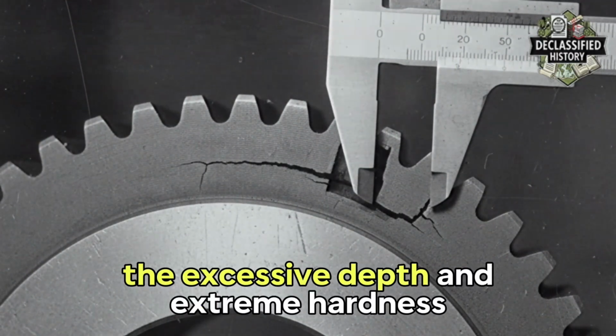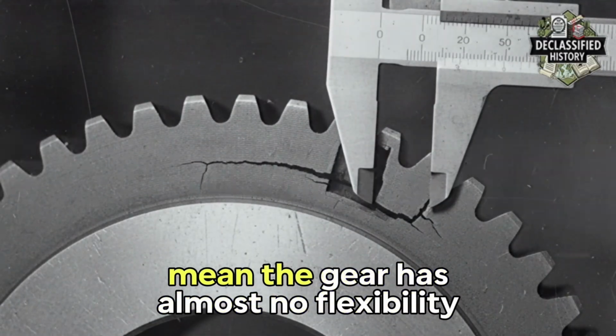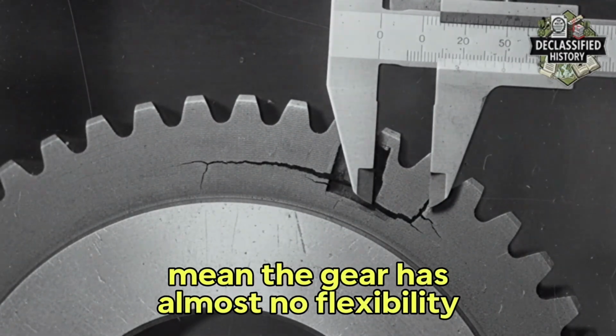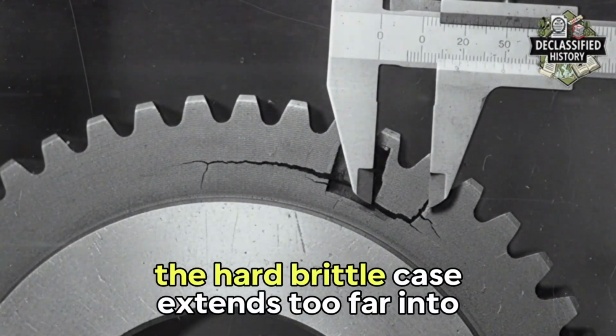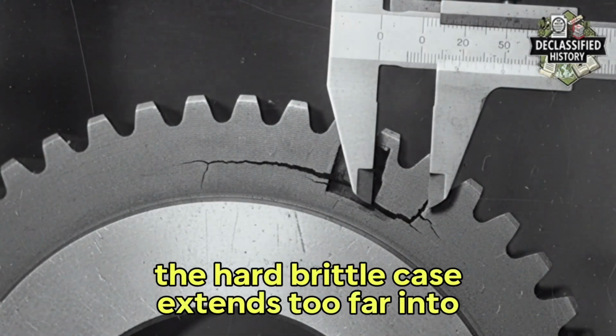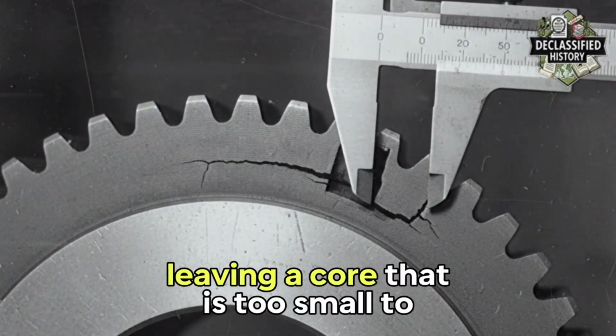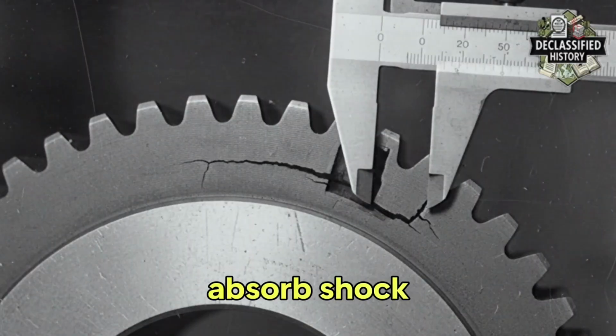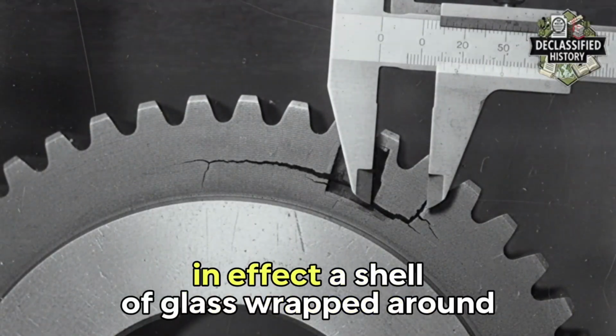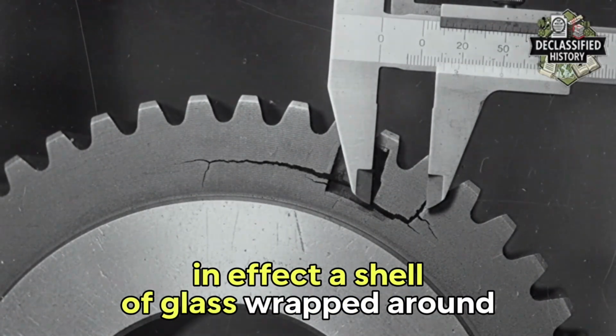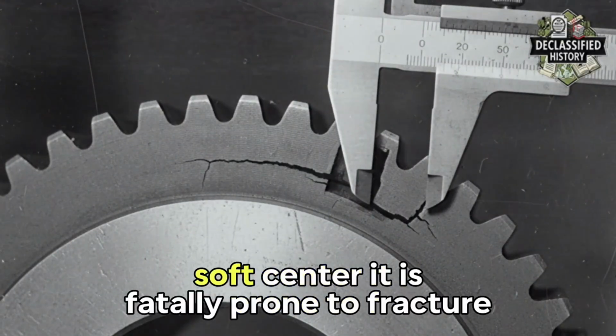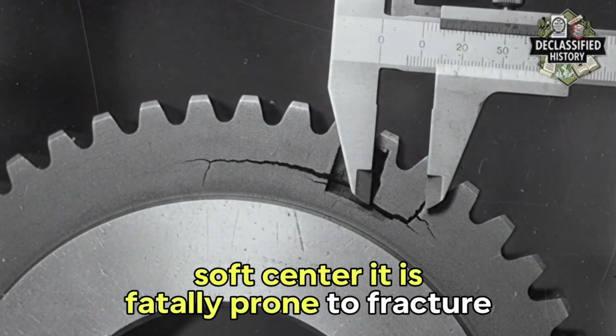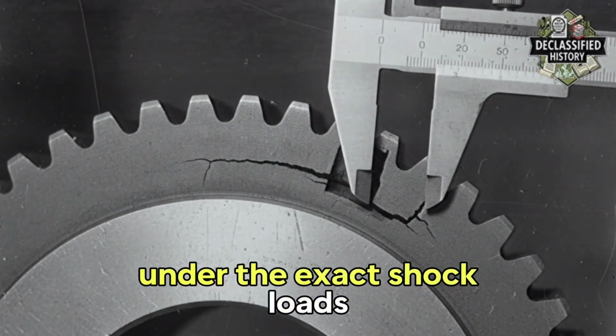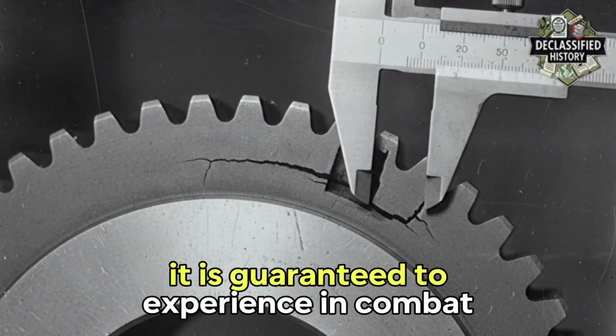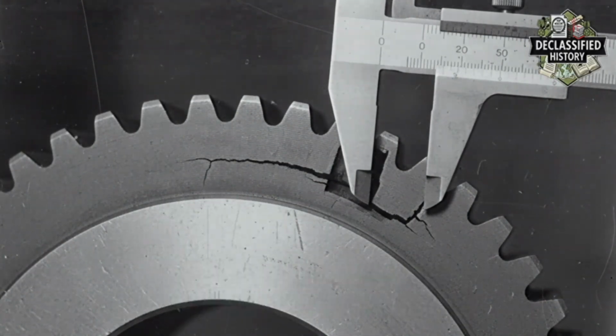The excessive depth and extreme hardness mean the gear has almost no flexibility. The hard, brittle case extends too far into the material, leaving a core that is too small to absorb shock. The gear is, in effect, a shell of glass wrapped around a small, soft center. It is fatally prone to fracture under the exact shock loads it is guaranteed to experience in combat.